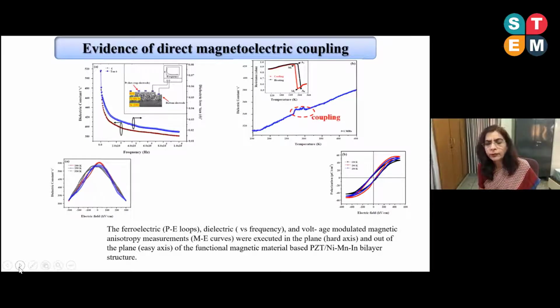The ferroelectric P-E loop, dielectric, and voltage modulated magnetic anisotropy measurements were executed in-plane and out-of-plane of the functional magnetic material in these bilayer heterostructures.